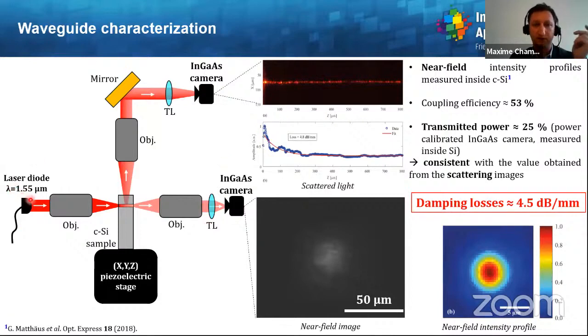We have employed another setup which relies on the emission of a continuous wave laser diode at 1.55 micron wavelength. Then the beam is focused to the waveguide and detected with a similar infrared microscope working in transmission as previously. And also we have another microscope allowing us to distinguish the scattered light. So here is typically what you see with the scattered light. So the damping losses can be estimated with this. And with the InGaAs microscope working in transmission, you can see the mode field and near field images.